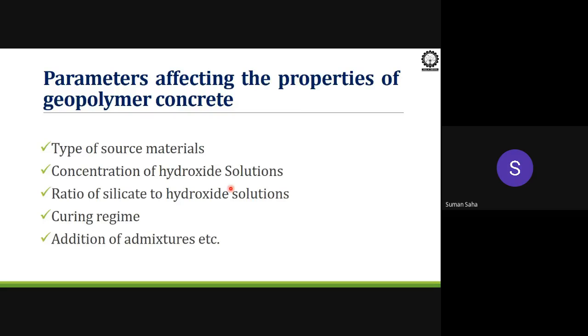Like if we are going to cast concrete tomorrow, then today itself this solution has to be prepared. For better understanding, if you prepare hydroxide solution, a lot of heat gets generated. So when we prepare the desired concentration of hydroxide solution, we need to let it cool down. Then we will incorporate silicate with our designed ratio. Then we'll mix it properly and keep it for 24 hours before producing geopolymer concrete.